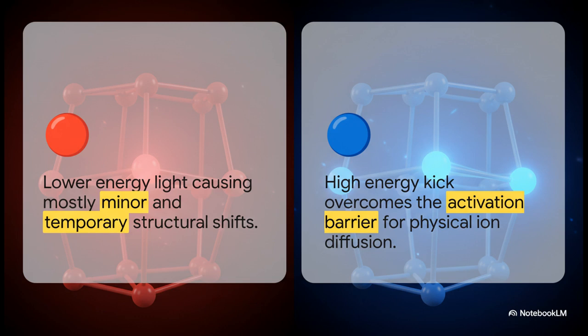But blue light at 470 nanometers packs a much higher energy punch. When a blue photon hits the perovskite, it doesn't just excite an electron. It provides what we call excess thermalization energy. Think of it as a massive thermal kick. And researchers discovered that this specific kick from blue light provides exactly the energy needed to overcome the activation barrier for ion diffusion. In plain English, blue light actually gives the ions inside the crystal the power they need to physically break away and migrate through the material.